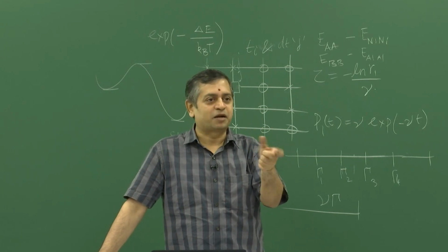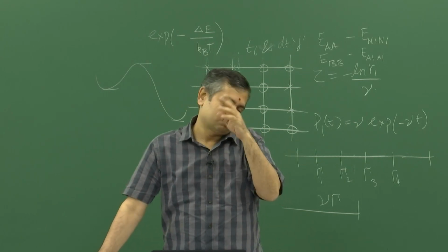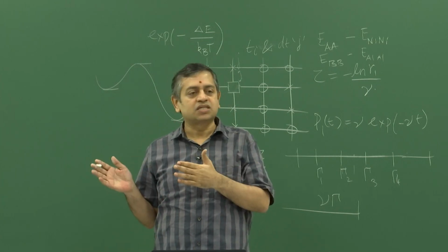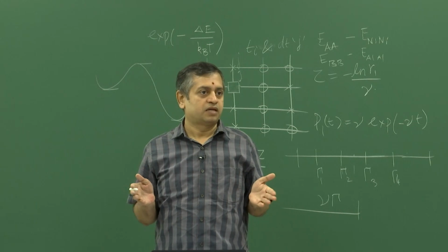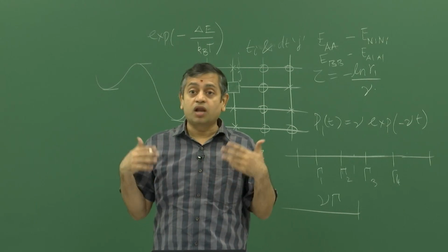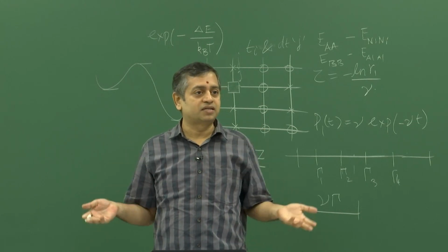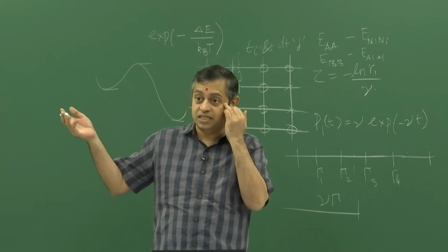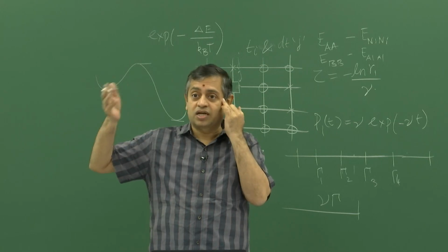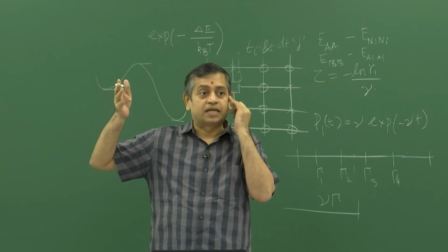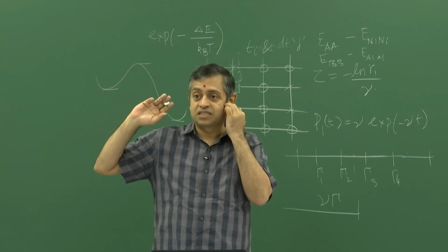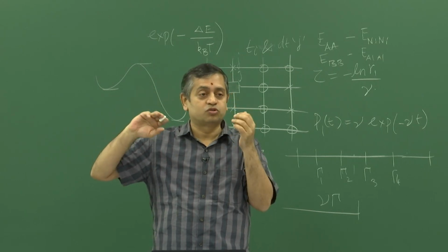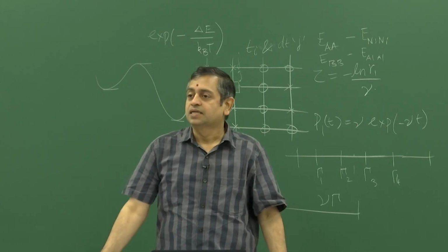these energy parameters. So, how many parameters you match, to that extent it is closer to the real system. But you have to remember that these are all approximations. Assuming only nearest neighbor bonds is an approximation, and only assuming pairwise interactions in a metallic system is also an approximation, right. In LJ you saw that you have to use EAM potential or something in molecular dynamics. LJ is not what you use for metals, EAM is.